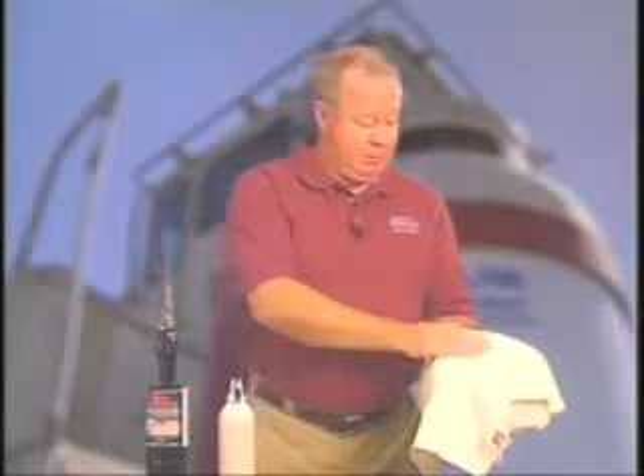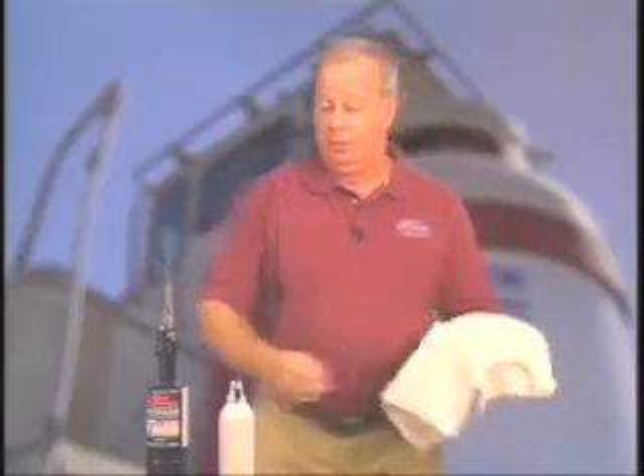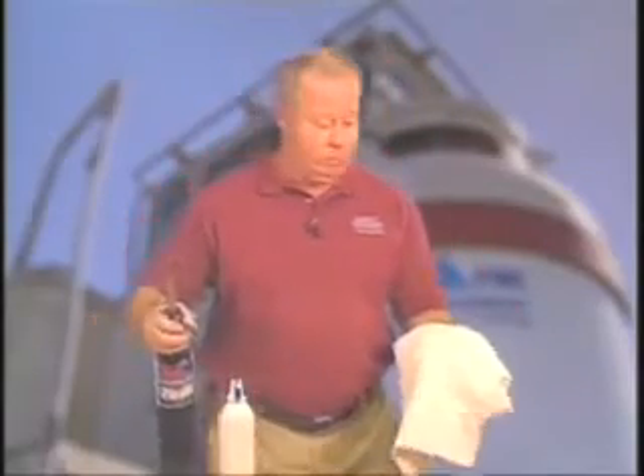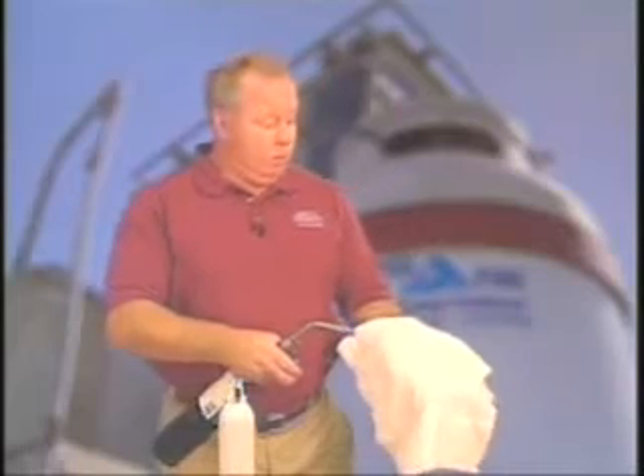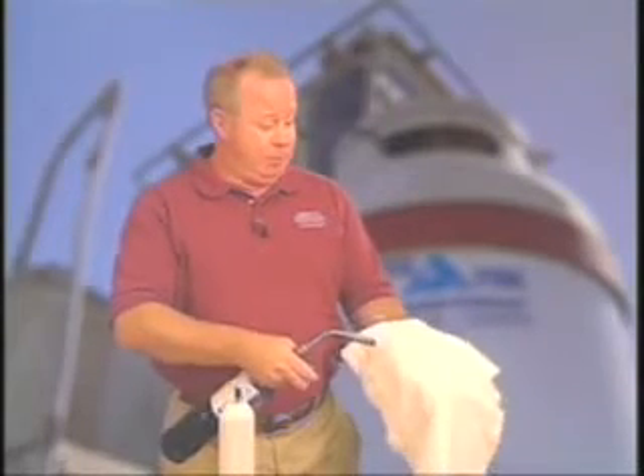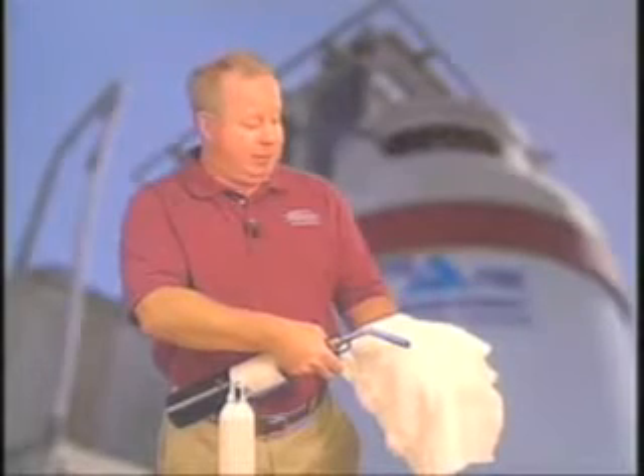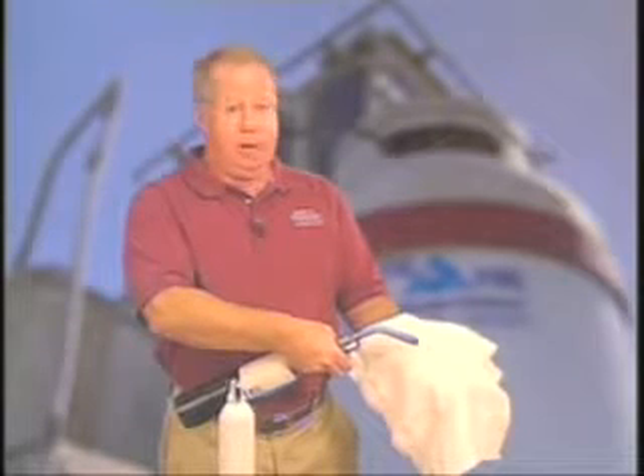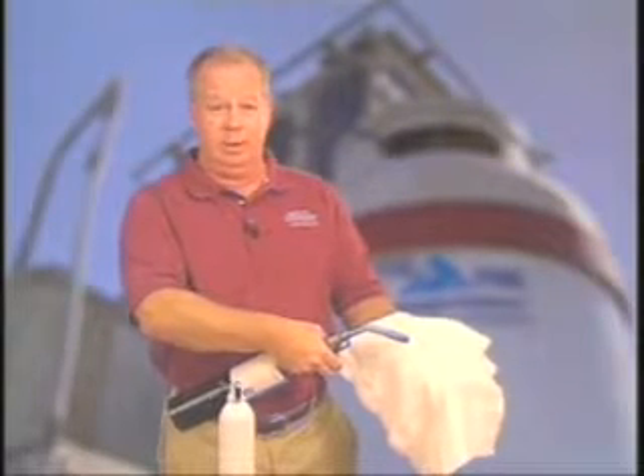Arctic Fire is a food-grade material, and once again it is designed specifically to spray on humans and in the environment. Once an object or surface is wetted with the Arctic Fire product, the Arctic Fire protects that surface from burning. Also, it sets up a thermal barrier or shield which doesn't allow the heat to penetrate this cotton terry material. The heat on this torch was measured at about 1900 degrees Fahrenheit, and at this point I feel no heat transfer to my hand whatsoever. Now the stain that you see is a result of the carbon buildup from the burning propane torch.